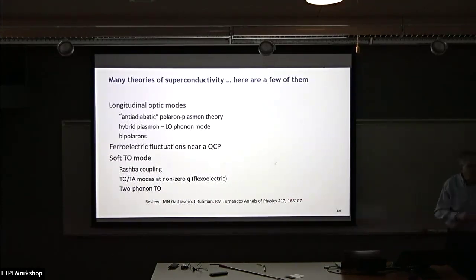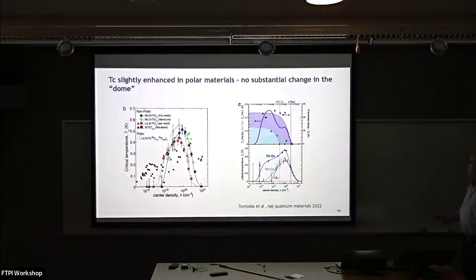There's stories associated with a couple of the longitudinal modes, which is clearly very strong. There's stories with ferroelectric fluctuations on a critical point. And then there are various attempts to couple to this soft TO mode, which is difficult to do because it's not dipolar and therefore doesn't couple. There's a nice story involving Rashba effect. There's, if you like, something that I would call flexoelectric, which is going to finite q. And there's two-phonon TO. There's another way of doing it. So all of these things are in principle plausible.